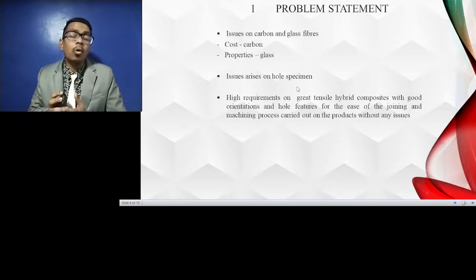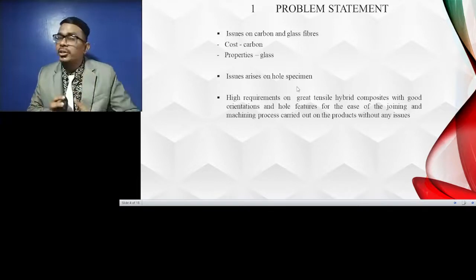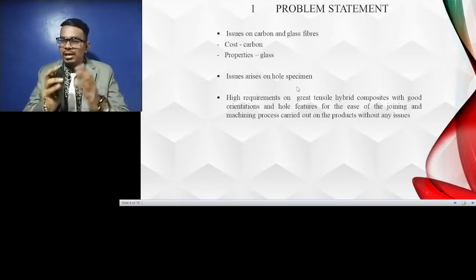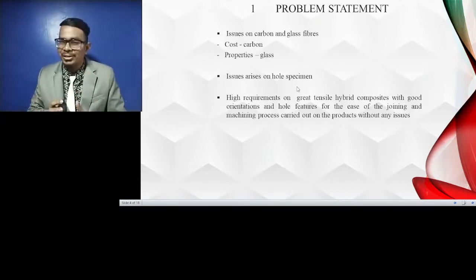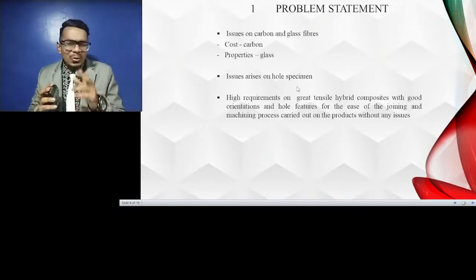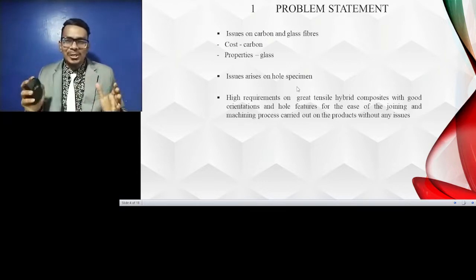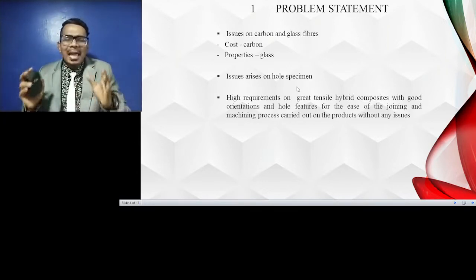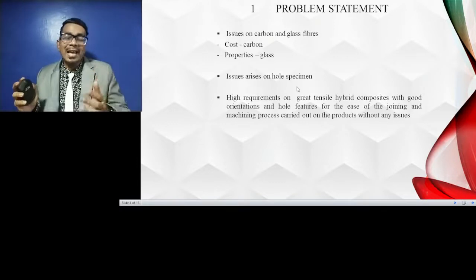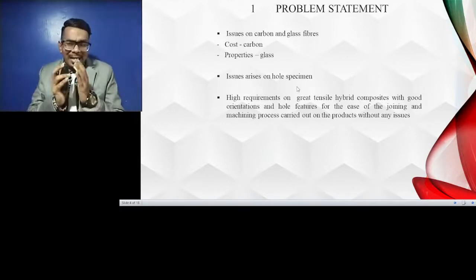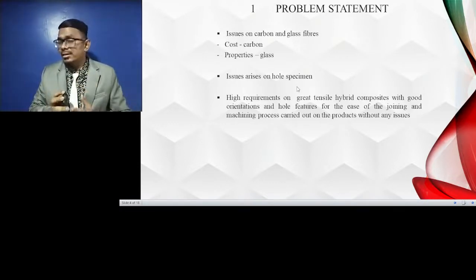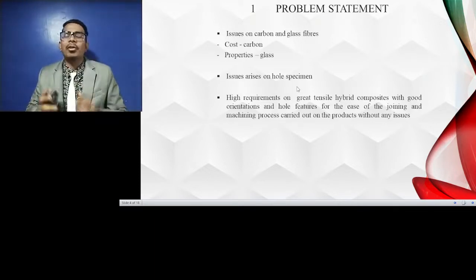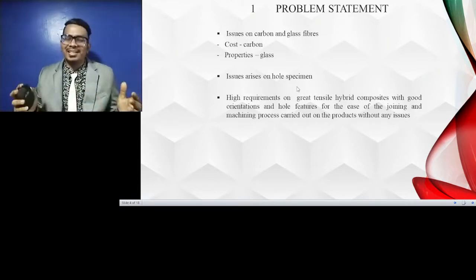Moreover, in practice, composite materials are frequently used in fabrication processes that necessitate drilling, which leads the specimens to become damaged. Damaged specimens do not necessarily mean they cannot be used. They may be damaged, but they have not yet failed or shattered. As a result, the damage resistance and the damage tolerance of the hybrid specimens at various orientations will be established in this investigation.